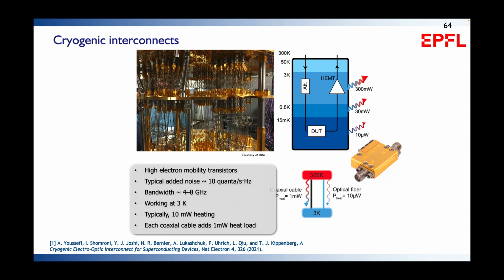If you look in one of these dilution refrigerators, you see literally hundreds of coax cables that go down from room temperature all the way to the mixing chamber. What you need to know about coax cables is they are excellent conductors for microwaves, but also excellent thermal conductors. And that means that with every microwave cable that goes down to the 4K stage, you have about 1 milliwatt of heating that comes from the environment due to thermal contact.